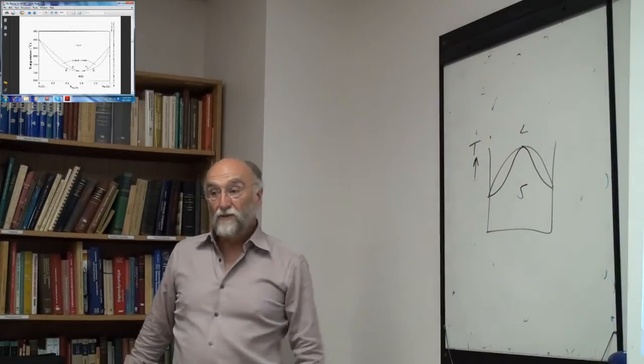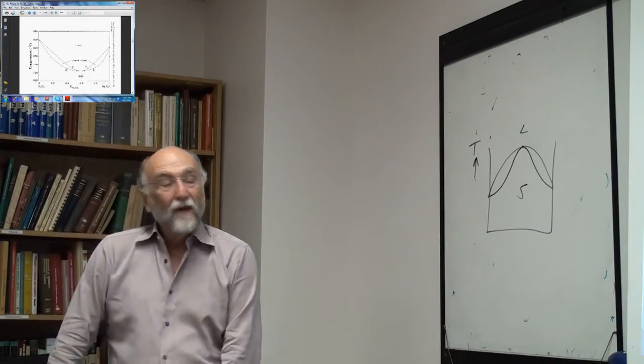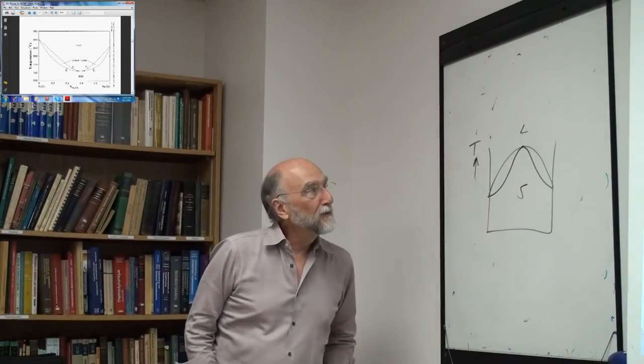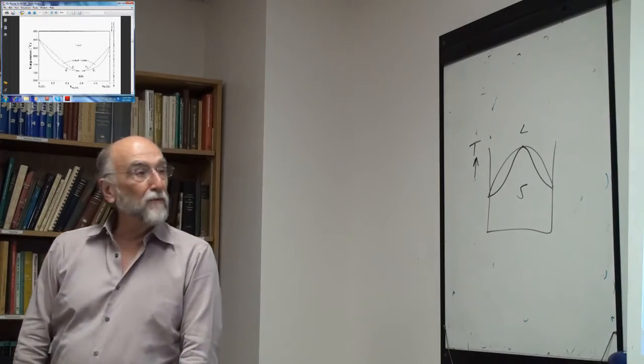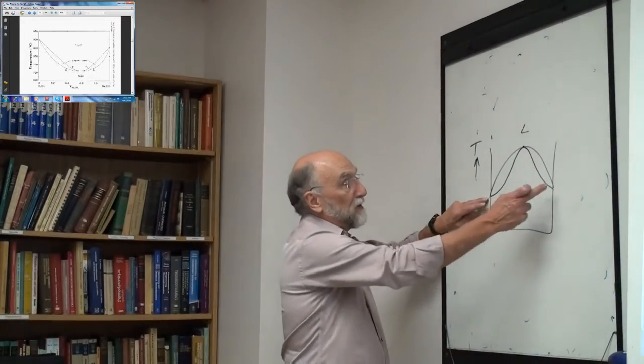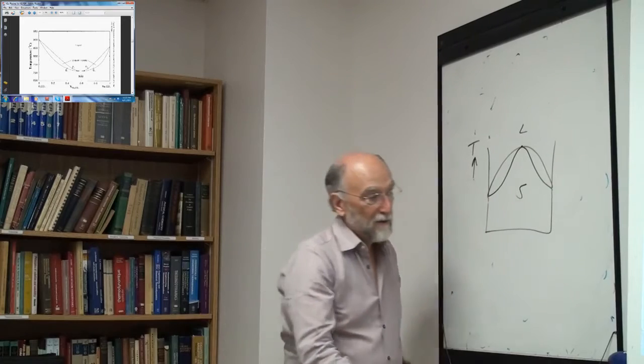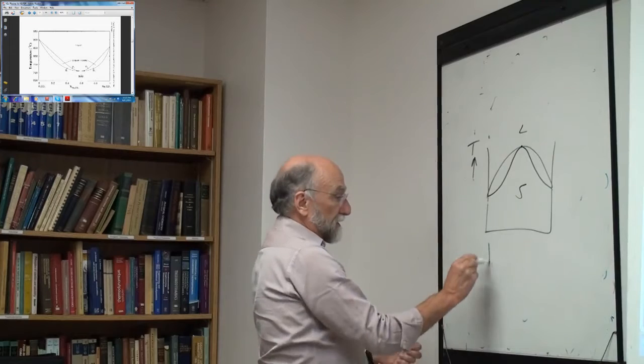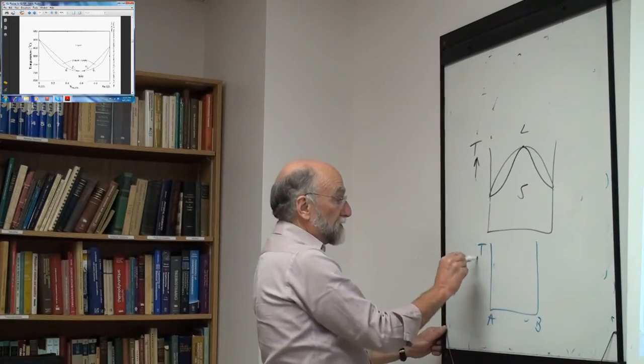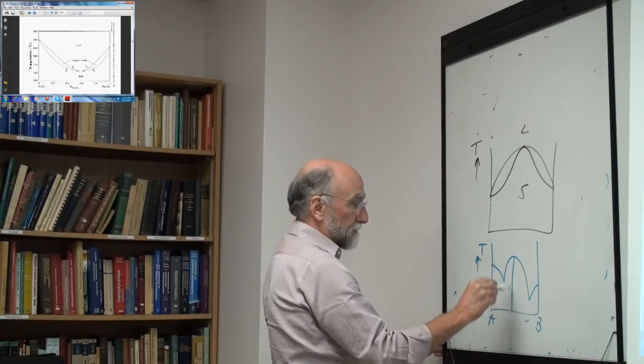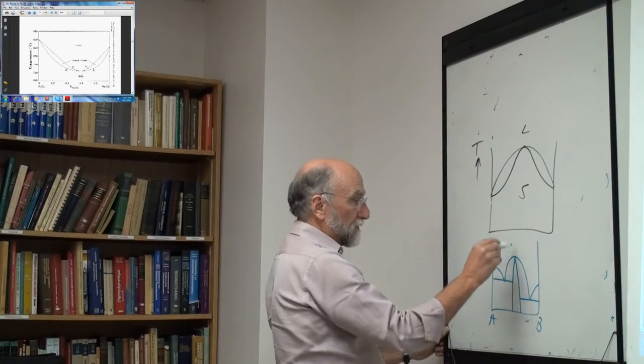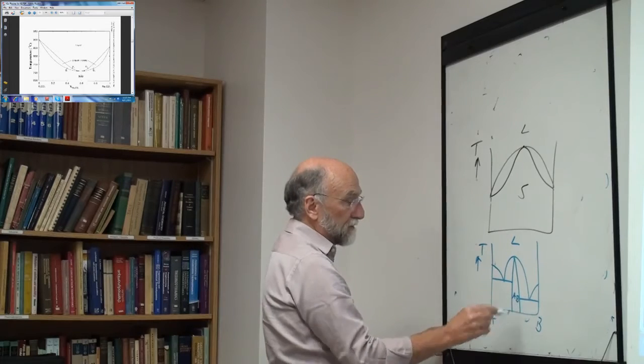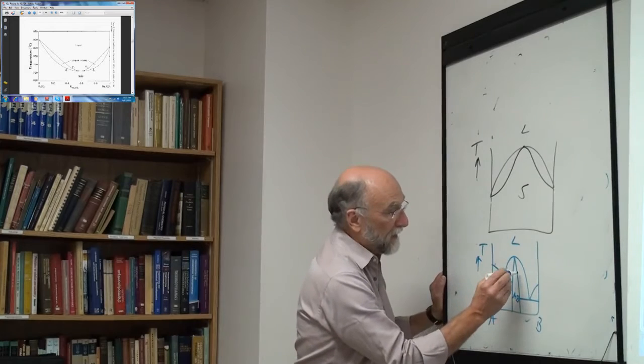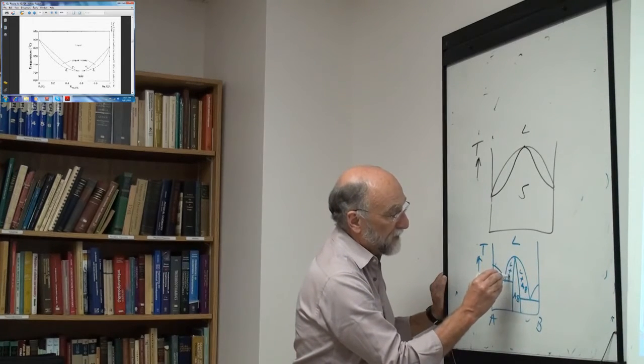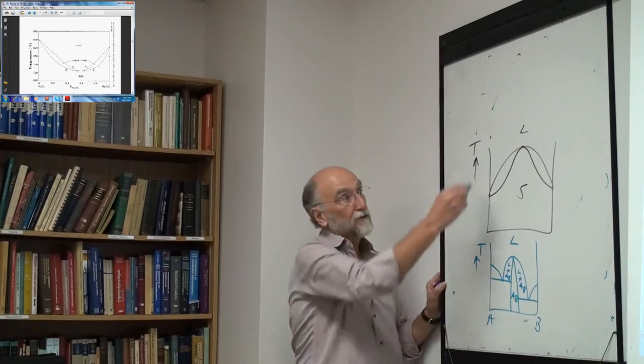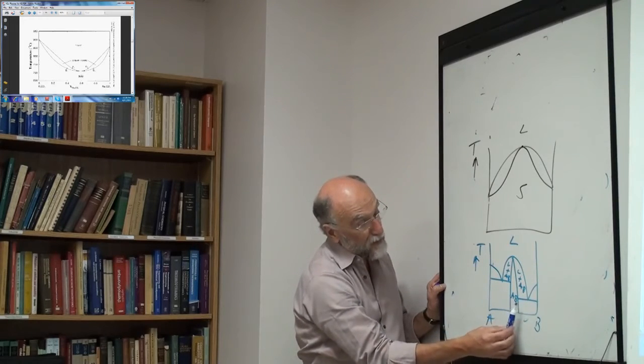Now, you do find maxima in two-phase regions all the time in phase diagrams, and that would mean that the solid is very stable relative to the liquid. When do you see a maximum in a two-phase region in a simple binary solid-liquid phase diagram? When I say you never see a maximum, I mean you never see a maximum above complete solid solubility. But you see all the time a diagram that looks like this. Say A and B, that's the phase diagram. Here I have liquid, here I have a compound AB, non-stoichiometric compound. So here you've got liquid plus AB, and over here you've got liquid plus AB, and this is clearly a maximum in a two-phase region, just like this. But it's above an intermediary phase, AB. It's not above the entire diagram.